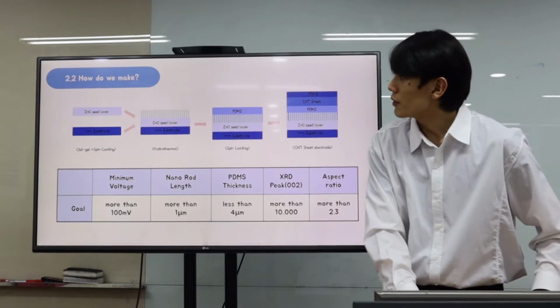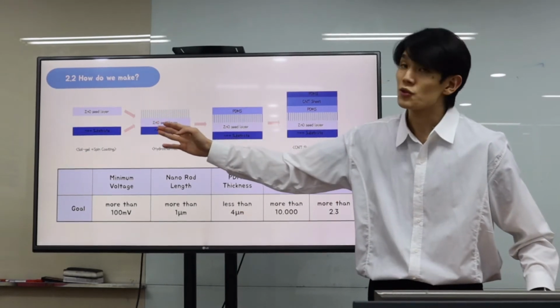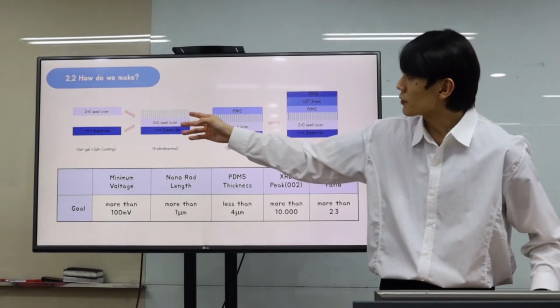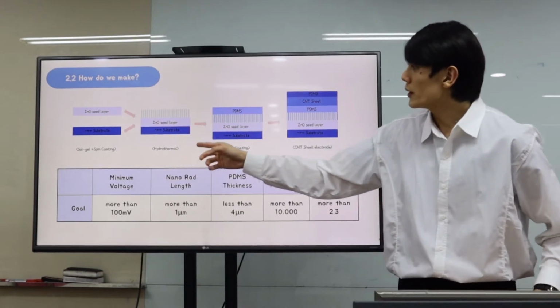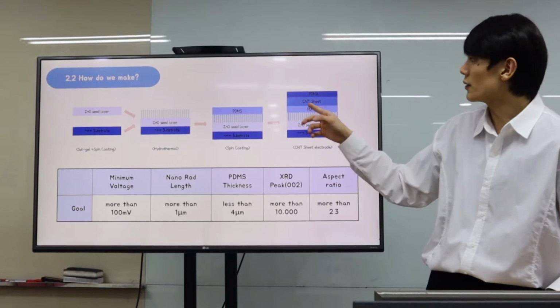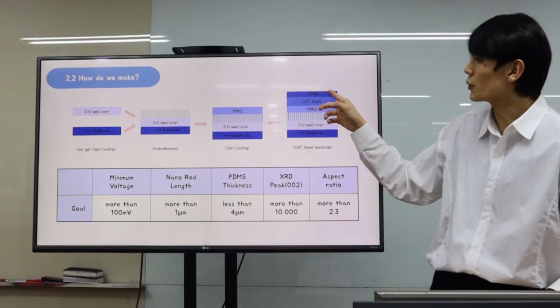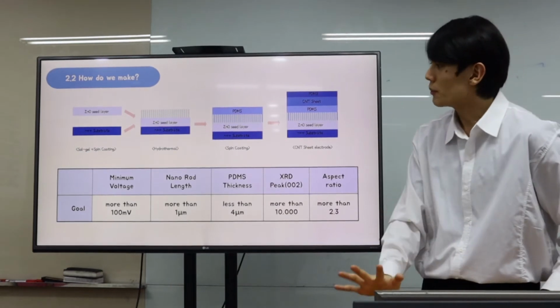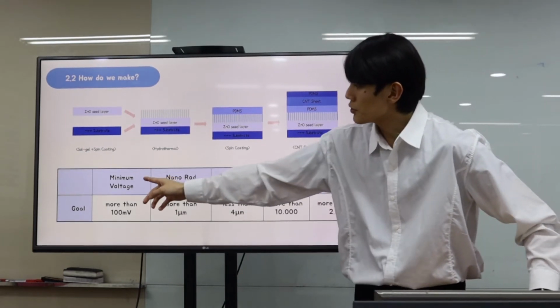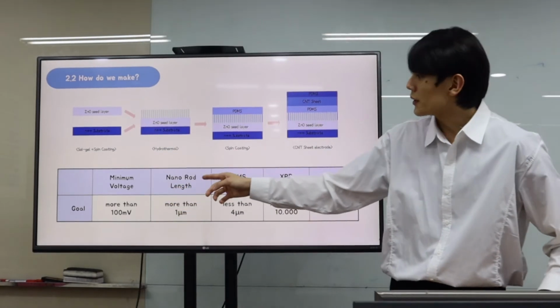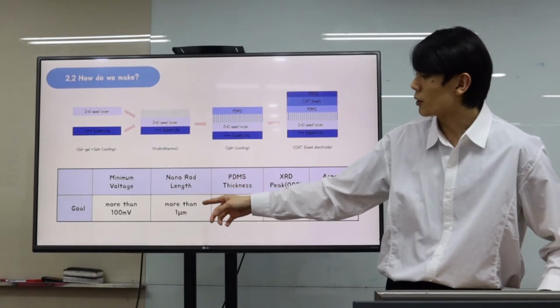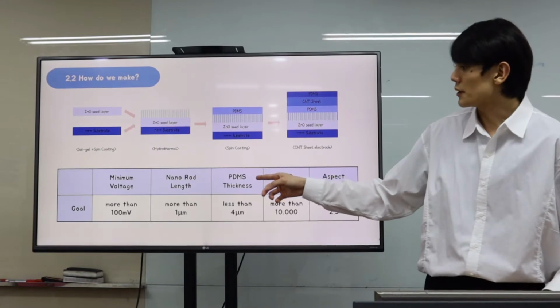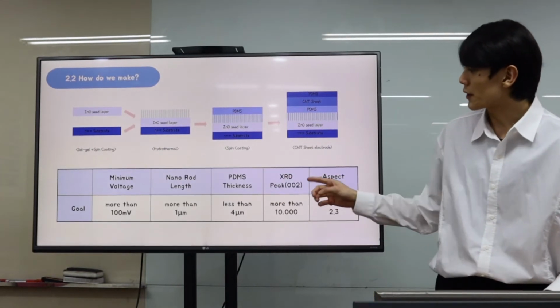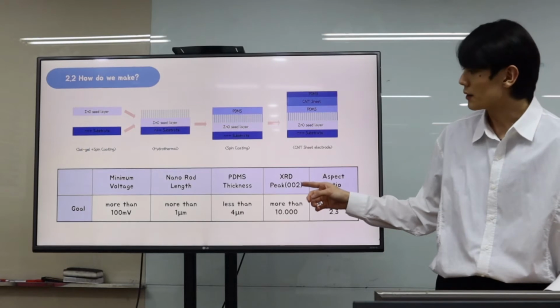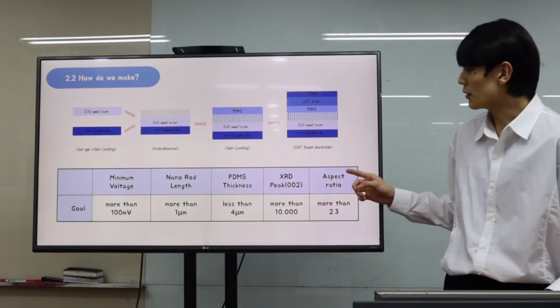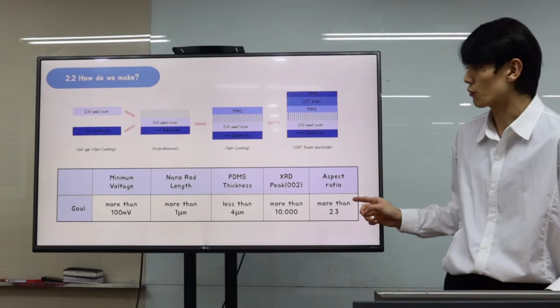Next, how do we make it? We make a zinc oxide seed layer by sol-gel and spin coating, the zinc oxide nanorod with hydrothermal, the PDMS with spin coating, and the CNT sheet with PDMS by spin coating. We have 5 goals to achieve. The minimum voltage must be more than 100 millivolts, and the nanorod length must be more than 1 micrometer. The PDMS thickness is less than 4 micrometers, the XRD peak on the 002 plane, the C plane, is more than 10,000, and the aspect ratio is more than 2.3.